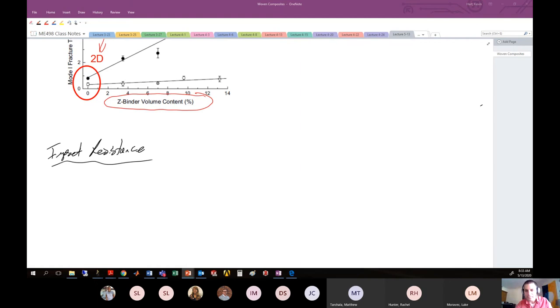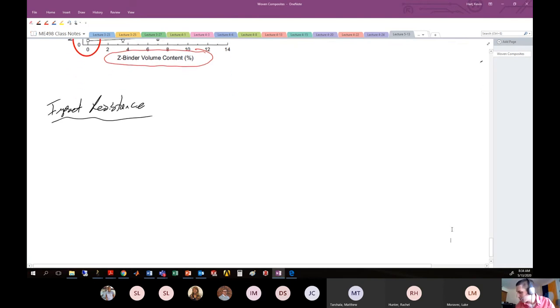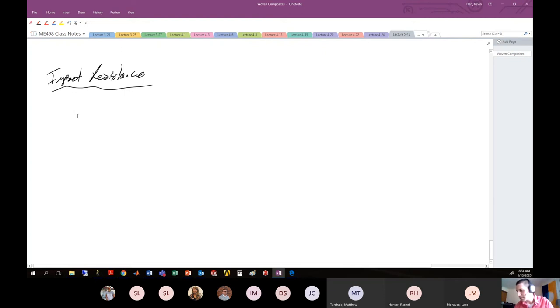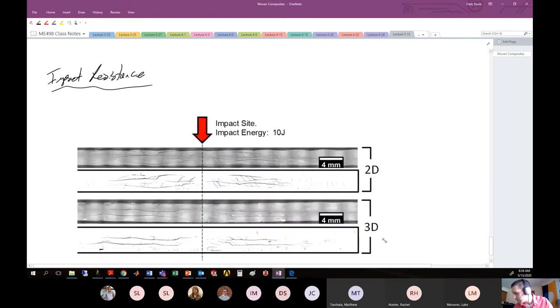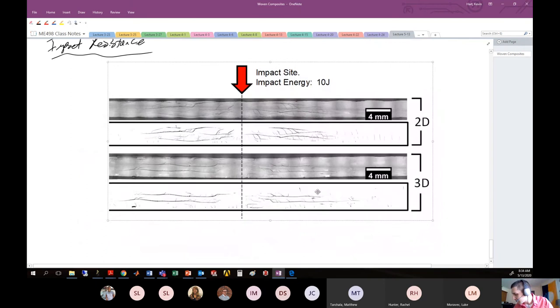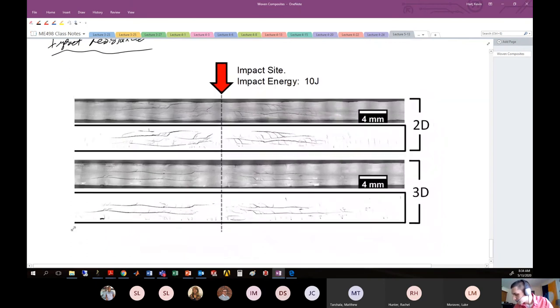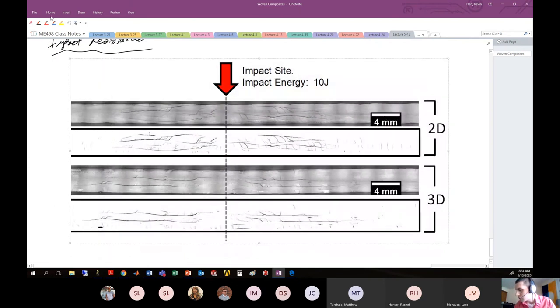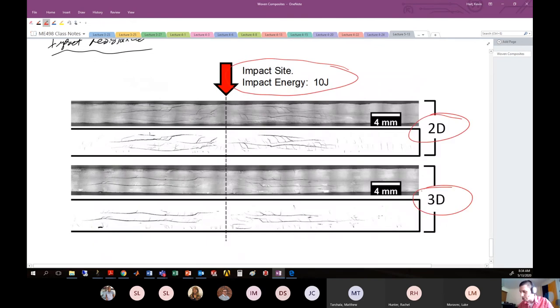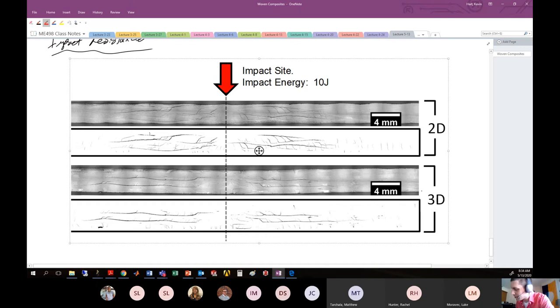All right. And so here is another image that kind of shows that impact resistance. So what you're looking at here is a series of impacted composites. And these are cross sections of impacted composites, and we'll show where the impact occurred and the damage that actually develops. So what you see here is an impact in what would be a 2D or a 3D woven sort of structure, all right? So the 2D structure, you see all these cracks that sort of emanate from where that impact site is.